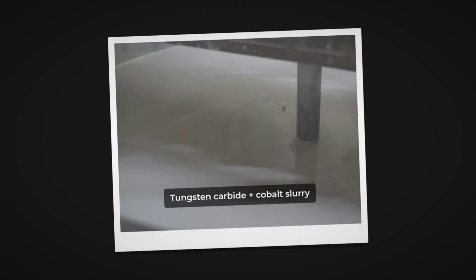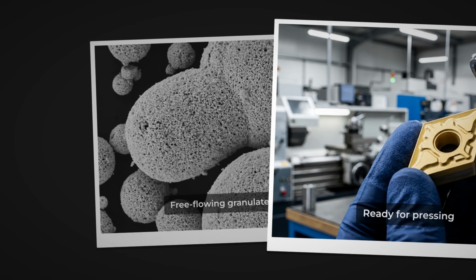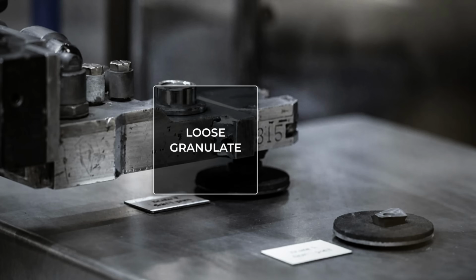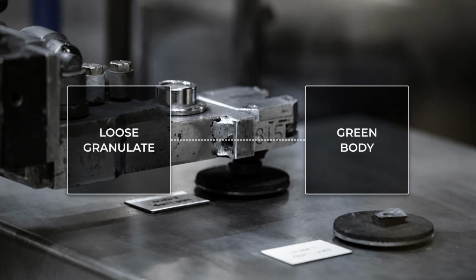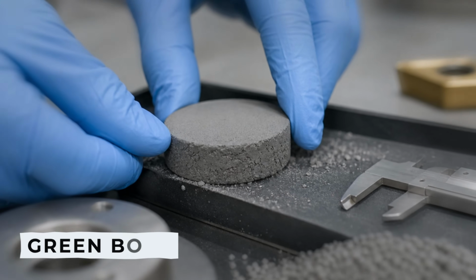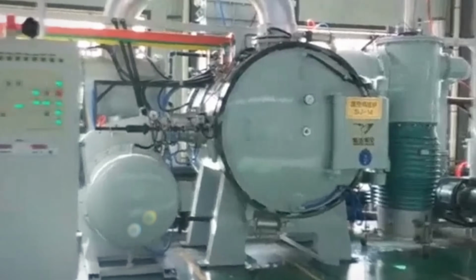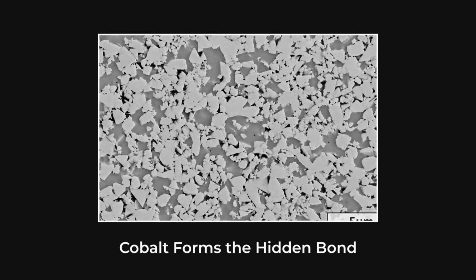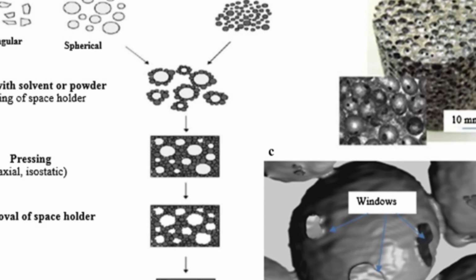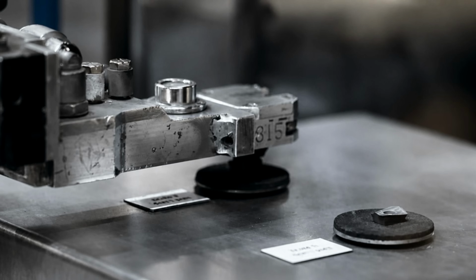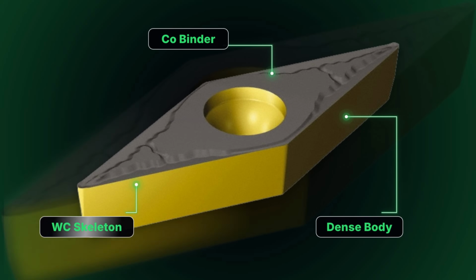So you blend it with cobalt powder, wet mill the mixture for hours in a ball mill, and spray dry the resulting slurry into a free-flowing granulate that looks a bit like instant coffee. That granulate gets pressed into a die under enormous pressure, producing a green body, a compact so fragile you can crumble it between your fingers. Then it goes into the sintering furnace. Somewhere between 1300 and 1500 degrees Celsius, the cobalt melts and flows into every gap between the carbide grains by capillary action, pulling the whole structure inward. The part shrinks by roughly half its volume. It comes out of that furnace as a single dense body of tungsten carbide skeleton locked in a metallic cobalt binder, and it will now cut hardened steel.